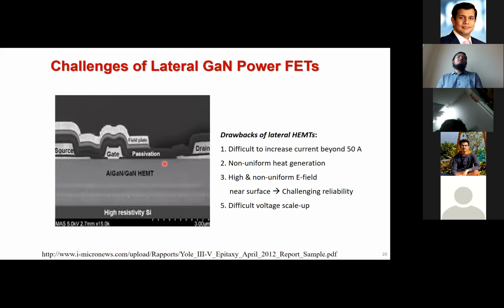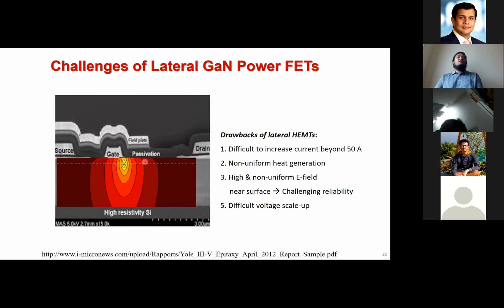The second, most intriguing problem is that when we operate at such high power, we also generate a lot of heat in the device, and that's detrimental. Since in these lateral devices the channel is right at the surface, if you plot the heat map of the device, it looks like this. The heat is really concentrated near the surface, near the gate region, while the bulk of the substrate is not used to spread the heat. This becomes an operating bottleneck for this device at high power.